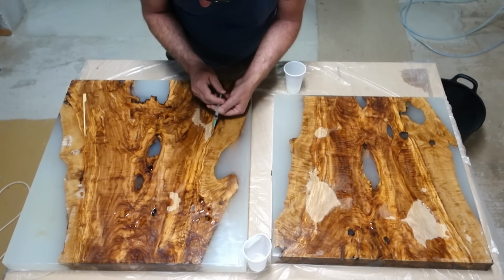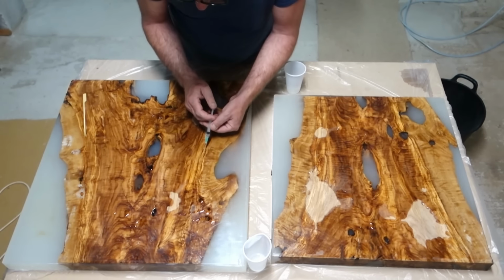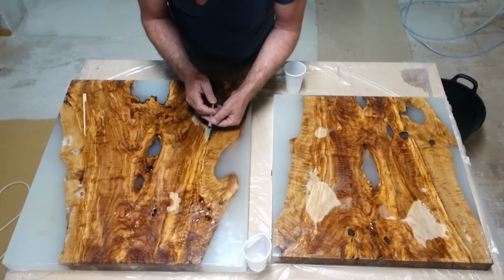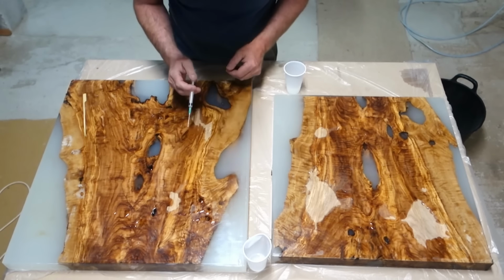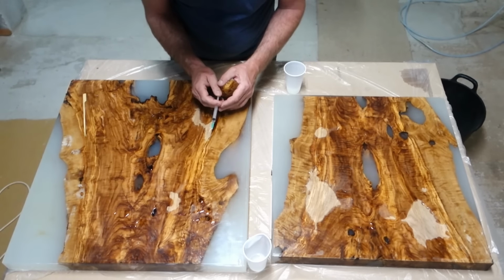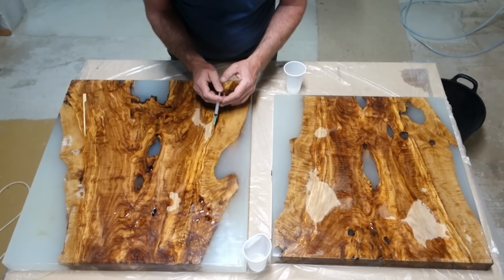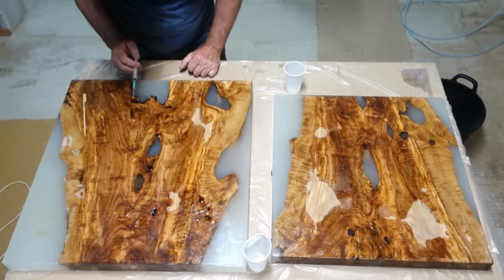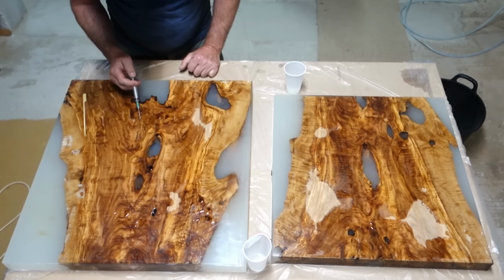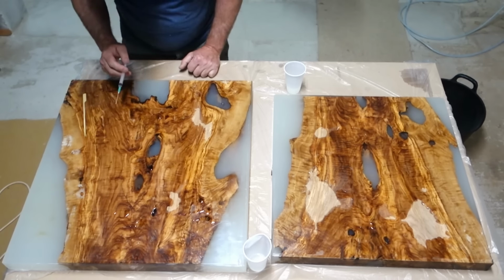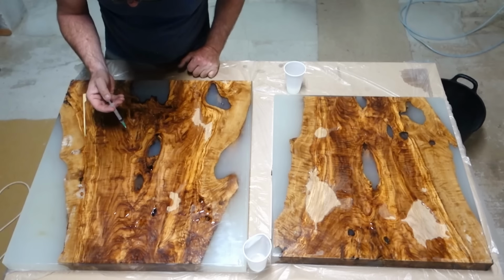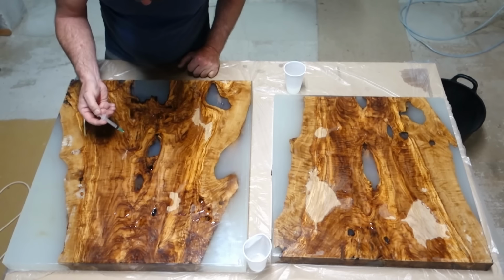I mean, there are some cracks that I've come across where you keep filling and filling with resin, and it doesn't seem to flow to the top. This is generally because the crack goes all the way to the other side, and when you lift up the piece, you'll see a damp patch on the underside. The way to get around this is to wipe the underside clean, make sure it's nice and dry, and then just put a bit of duct tape over it, a bit of packing tape or so. This will create a dam, and then you'll be able to pour the resin from the top without it leaking out of the bottom.